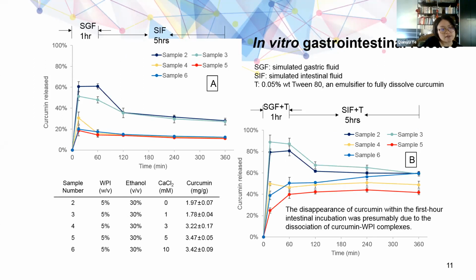This slide shows the release characteristics of curcumin from curcumin WPI complex microparticles in the simulated GI tract. In Figure 1, initial burst release of curcumin was observed in all samples, caused by the surface distribution of curcumin in matrix-type microparticles. Ethanol-induced desolvation improved the digestibility of WPI, leading to a rapid release of curcumin observed in samples 2 and 3.